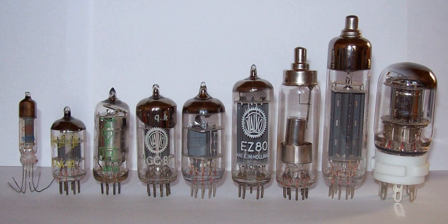Modern tubes are constructed with getters, which are usually small, circular troughs filled with metals that oxidize quickly, barium being the most common. While the tube envelope is being evacuated, the internal parts except the getter are heated by RF induction heating to evolve any remaining gas from the metal parts. The tube is then sealed and the getter is heated to a high temperature, again by radio frequency induction heating, which causes the getter material to vaporize and react with any residual gas.